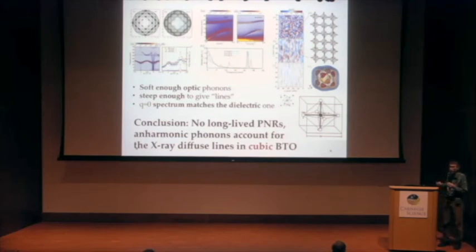It's off-centered. But if you look at how many of the titaniums are in these positions, only 5%. So 95% have energy which is over the barrier between them, so they are everywhere around. So most of the titaniums are just running around, so the barrier is very small.